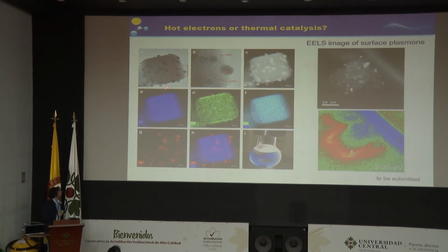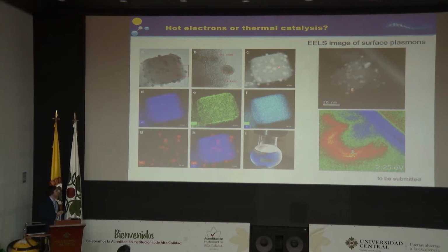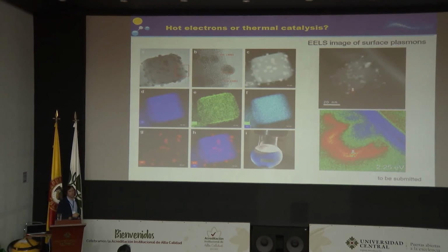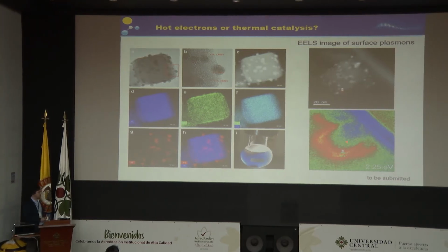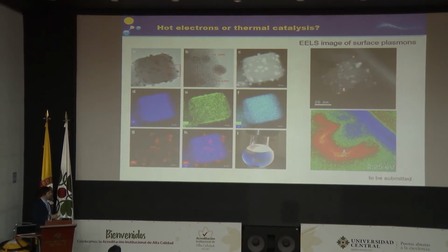Okay, these are our really nice materials, which my postdoc prepared. Through a wet chemical method, we deposit many platinum nanocrystals, 3 nanometer average size, on a 50 nanometer titanium nitride cube, which of course shows plasmonic resonance. Here you can see that we use free electrons to excite the dipolar surface plasmon resonance through the use of EELS. You can see the propagation of the electric field around the titanium nitride cubes, which also involves all the platinum particles deposited on the surface of the catalyst.